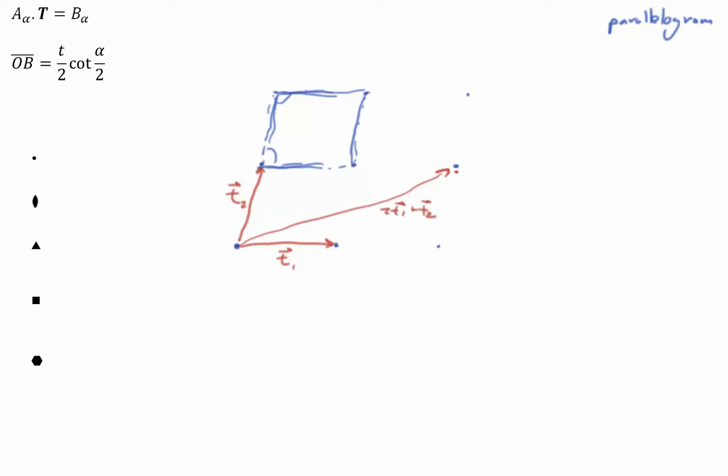Okay, so let's think about what happens if I start introducing two-dimensional rotation axes. If I introduce a two-fold rotation axis on the lattice point, I would necessarily have one on the other lattice point. And remember, previously we generate a new two-fold rotation axis that is halfway along this lattice point, sitting on the lattice vector. The same thing would happen here. This two-fold rotation axis would be translated up to this lattice point, and I would have another two-fold rotation axis along that translation vector. These two-fold axes would be recurring throughout all two dimensions, but these are entirely consistent with a parallelogram lattice.